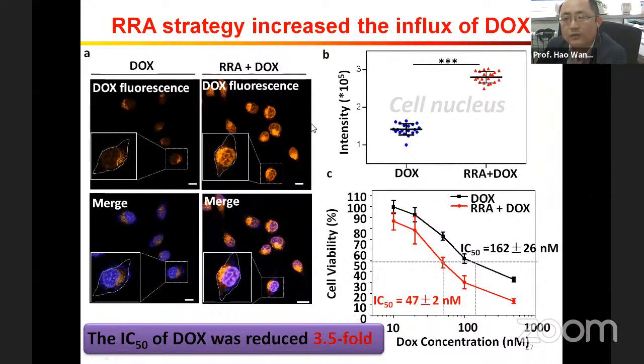Finally, we just use our material with the conventional DOX. This DOX is a chemo drug, quite normally used. If we just use the pure DOX, in the cell nuclei we barely see the drug signal, right? The signal is quite weak. But when we use both our material and the DOX, we can see the DOX signal in the nuclei is much, much stronger. In that case, it means that our molecule can help the chemo drug get inside the tumor cell.